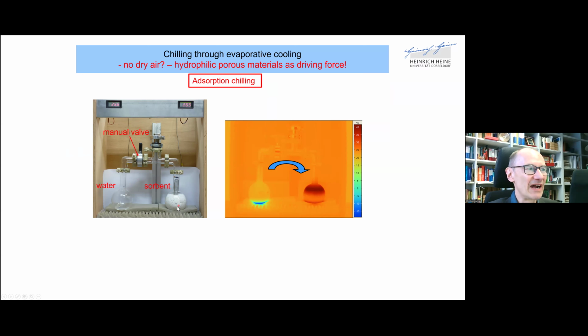And here's a simple device which has a water-filled flask, water at the bottom here, and a sorbent material in another flask. There's a manual valve which separates both of them. And once you open the valve, the infrared image to the right shows what happens. So this water-filled flask cools down. Actually, it doesn't take long, within less than a minute, to sub-0 degrees centigrade.